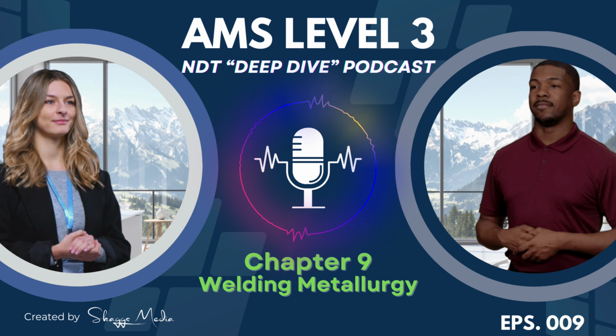First is the need for a small amount of delta ferrite in the weld metal as it solidifies. Austenite itself is prone to hot cracking or solidification cracking right as it freezes. Having a little bit of ferrite mixed in, usually targeted between 4% and 10%, measured as a ferrite number or FN, changes the solidification mechanism and prevents this cracking. Since austenite FCC is non-magnetic and ferrite BCC is magnetic, inspectors often use a calibrated magnet, a magnetic gauge, right on the weld to verify the ferrite number is within the required range. Okay, so ferrite number check for hot cracking prevention.